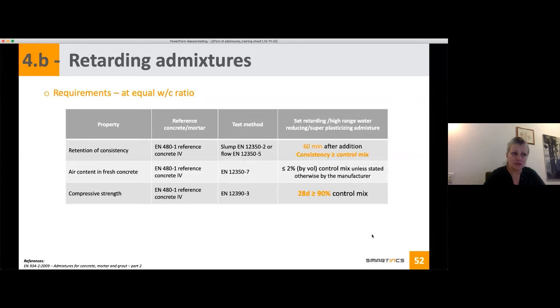For the special category of set retarding super plasticizing admixture, you have an extra set of requirements, and this is for equal water to cement ratio. The first table I just presented was equal consistency. Now we have equal water to cement ratio, which means that you have some extra requirements relating to the consistency, and that comes with a retention. With a set retarding admixture, it means that 1 hour after addition of your admixture, your consistency should be at least the same as your control or higher. The air content is a constant one, no more than 2% by volume.